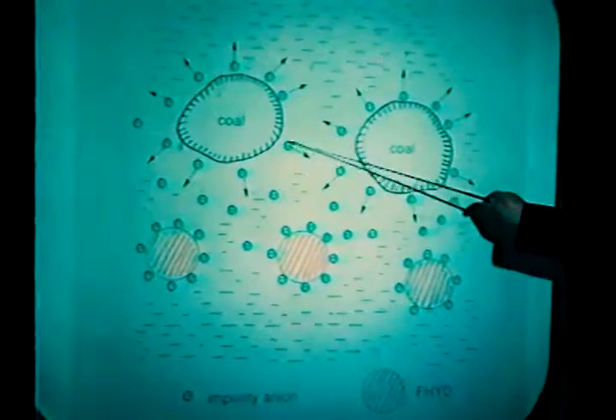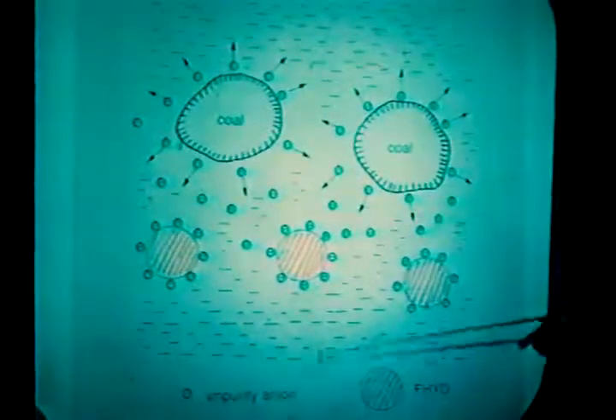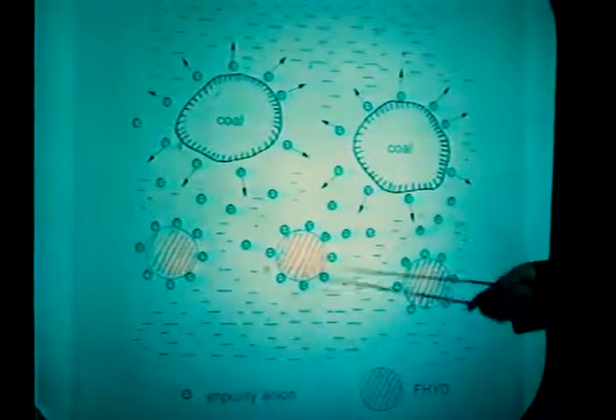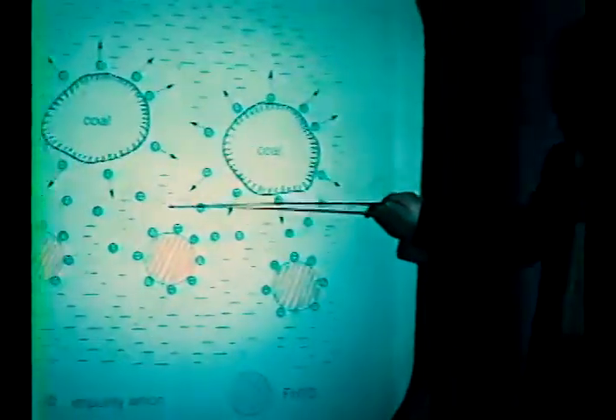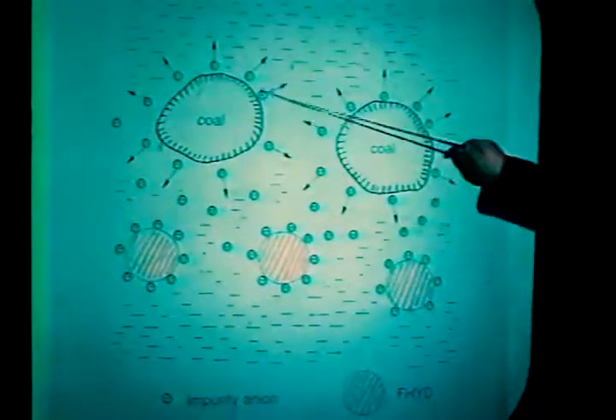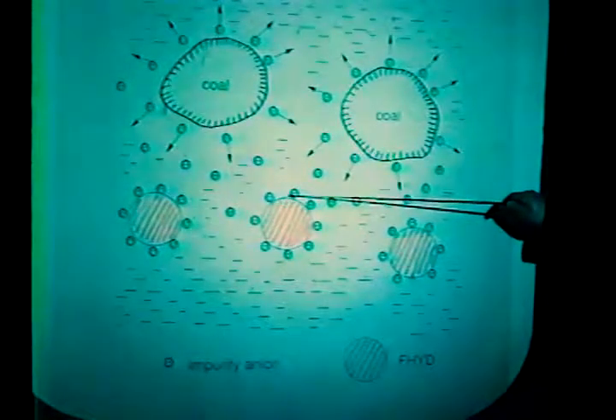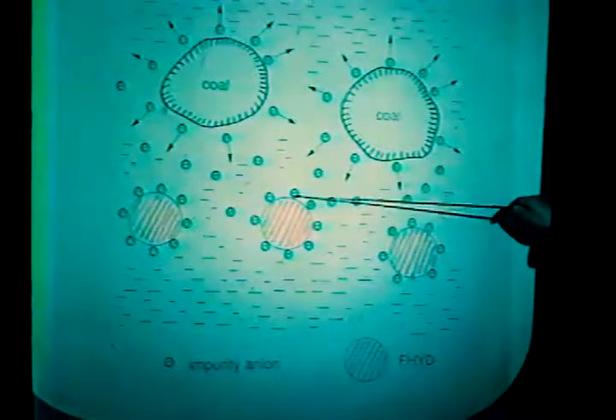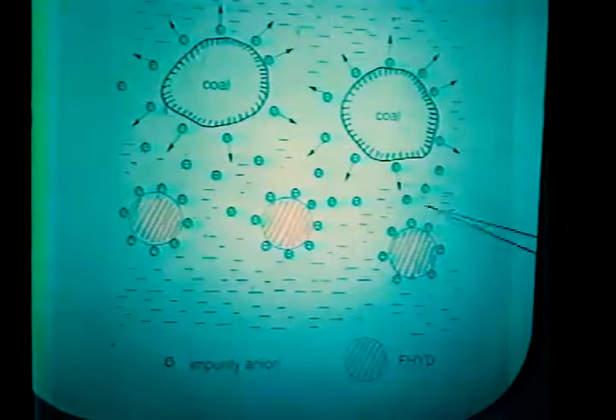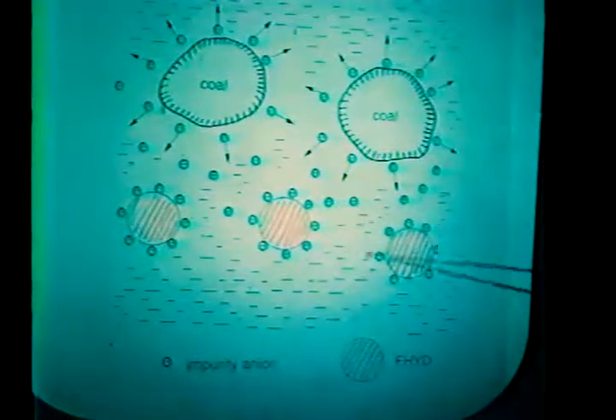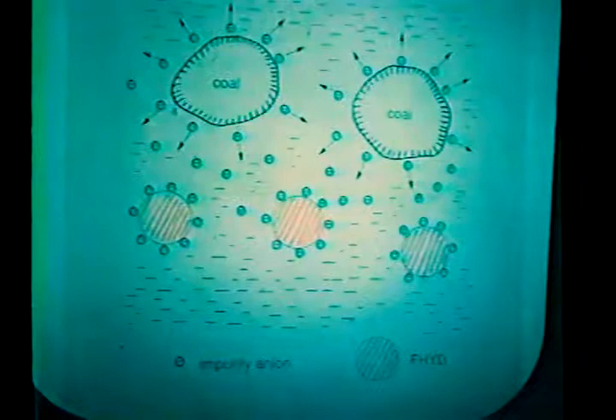Now, if you put coal in solution, inevitably some ions will be dissolved in the solution. These are, let's say, ions - could be organic or inorganic. And these ions, when you put ammonium hydroxide into the solution, you will have ferrihydrite, and this impurity will deposit at the surface, adsorb at the surface. So basically, this method will produce a binary ferrihydrite catalyst similar to the catalyst we mentioned.